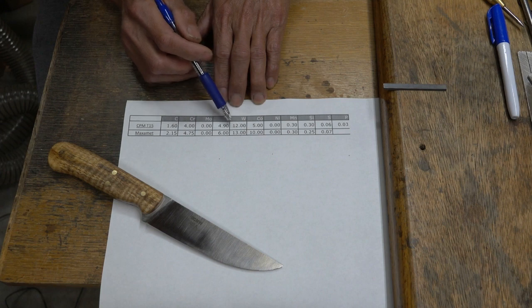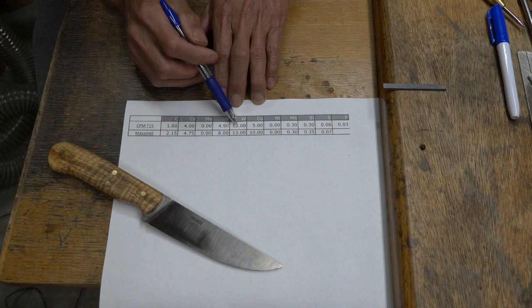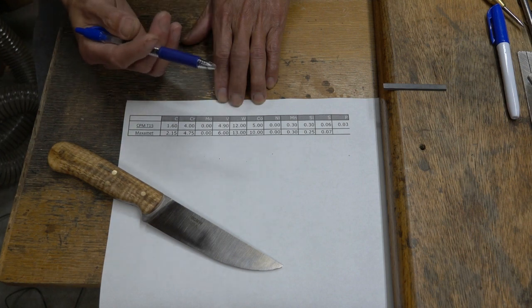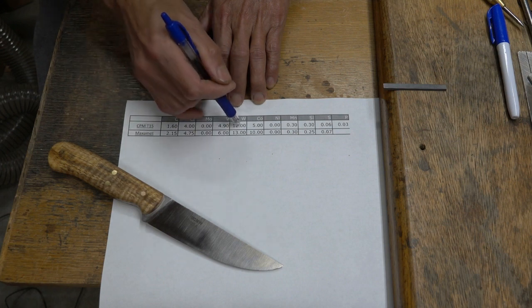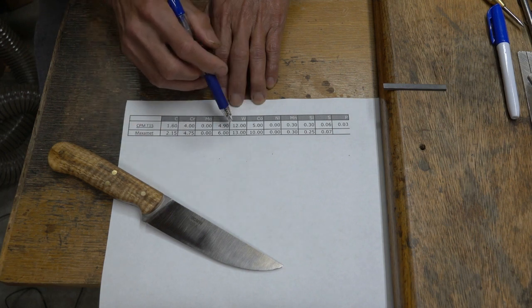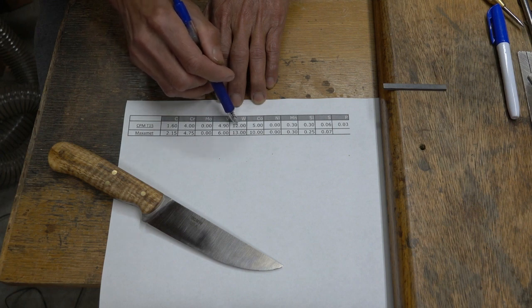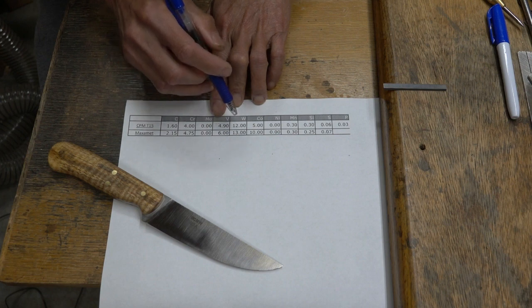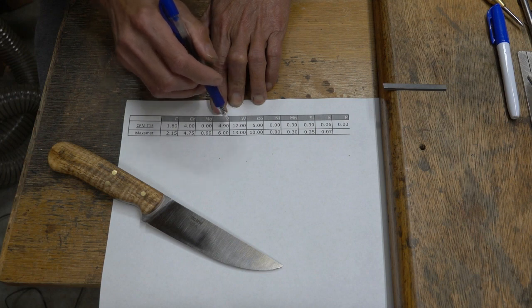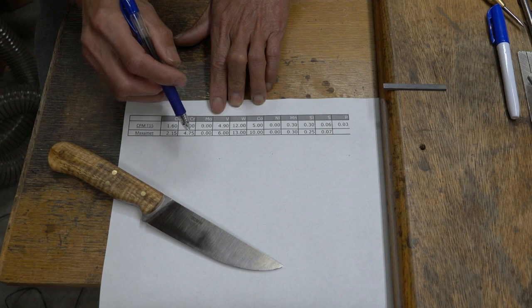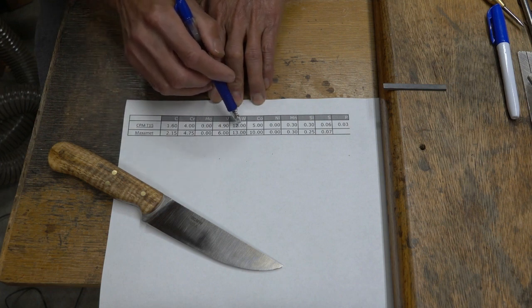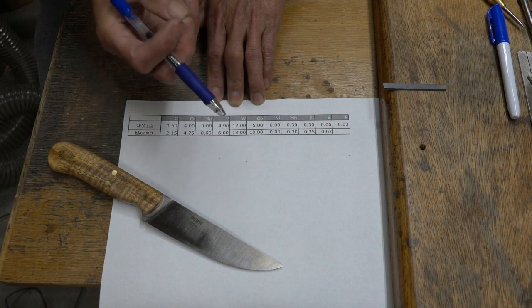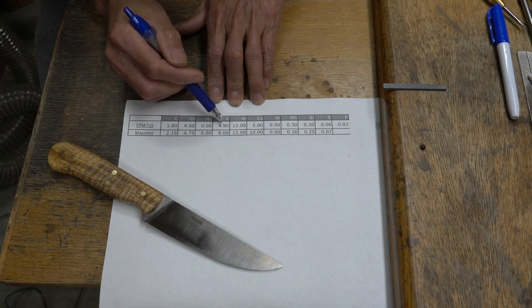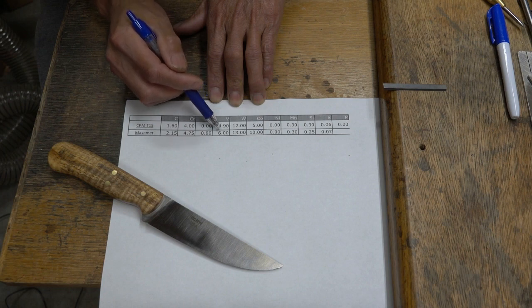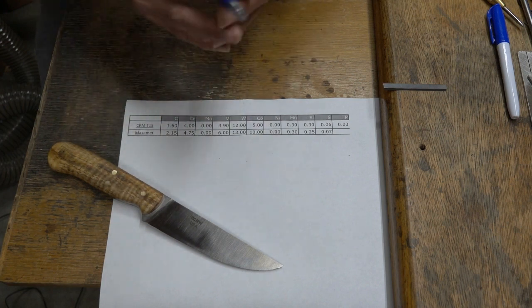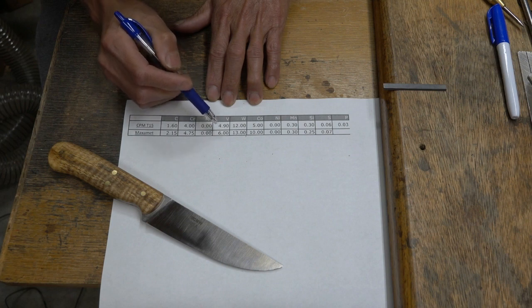Tungsten is, because these are percent of mass, 12% of tungsten, if you do a per-atom count, 1 atom of tungsten is about 3 times heavier than vanadium. So therefore, 12% mass percent of tungsten has about a similar atomic count as 4% vanadium mass percent. In other words, atom-wise you have 2 types of carbide that will provide a lot of coverage. The vanadium carbide I expect to be, given that it would form itself and not composite and combine with a bunch of things together, about between 1 to 3 micron.